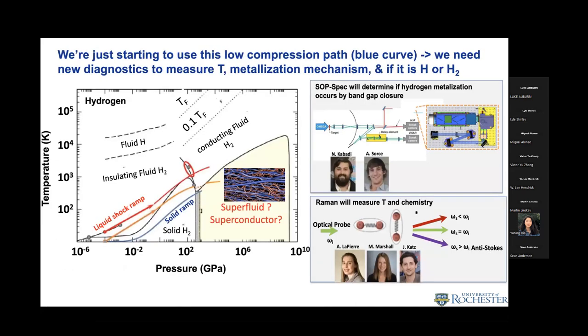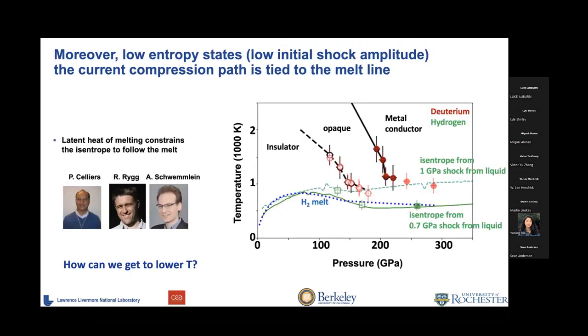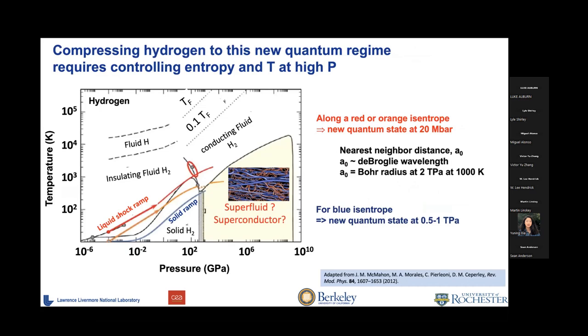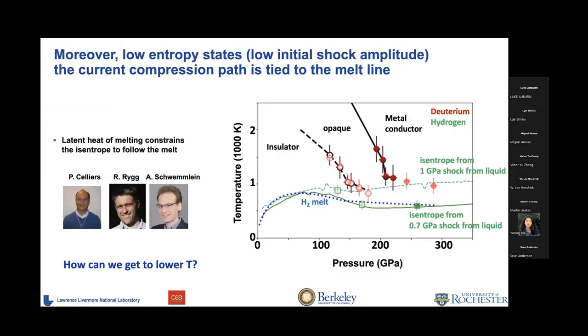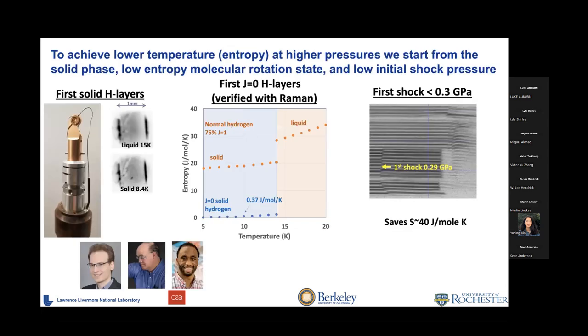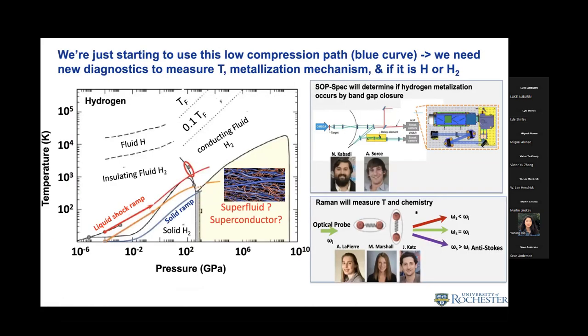In other words, if I go back here, what we're trying to do is stay down here so we can get into the superfluid region. To do that, we have a bunch of folks working on ways to create a solid phase first. Then it turns out hydrogen has a bunch of quantum spin states. So we manipulate the spin states so that it's in a low entropy state, and then we launch the smallest pre-compression wave initial shock that we can. When we add all of these things up, we're able to get on a very, very low isentrope. So in the next year or so, we should be able to access this range. And so we're developing a whole bunch of different experimental techniques.